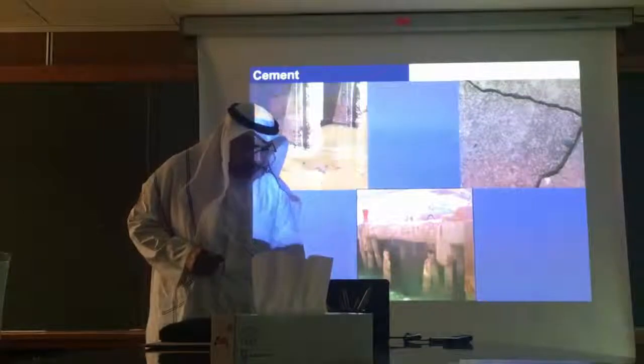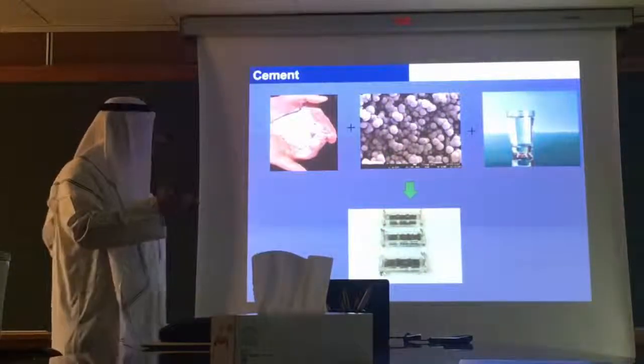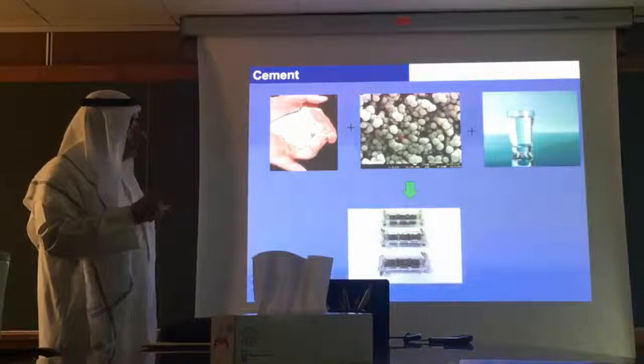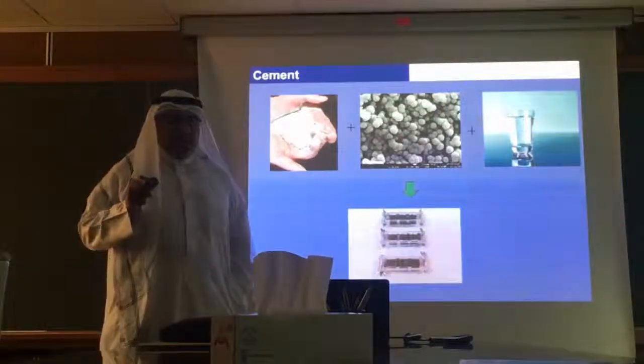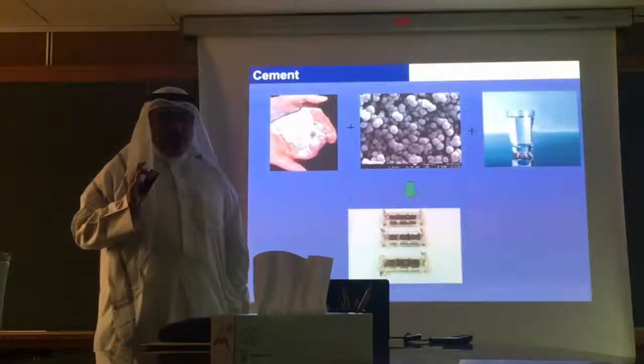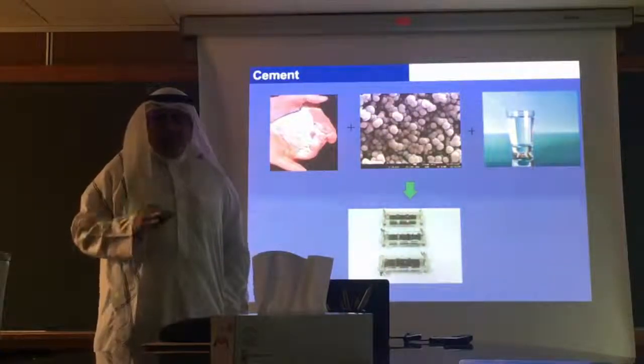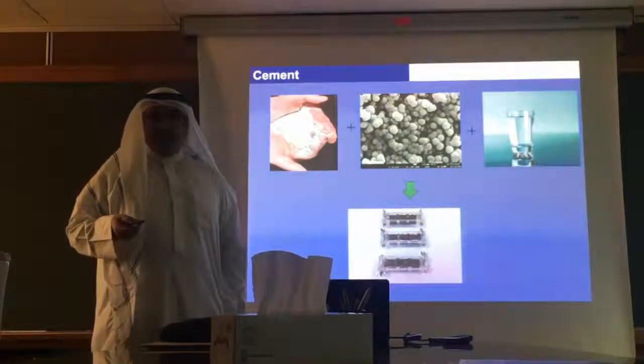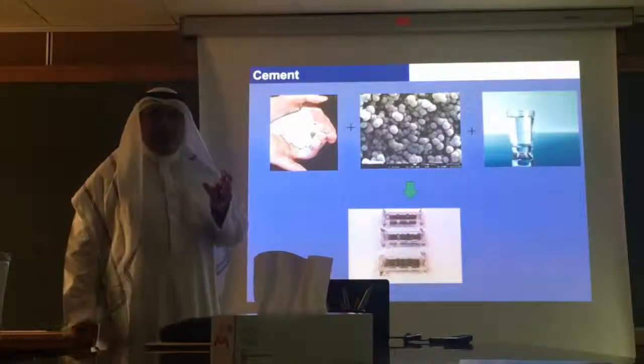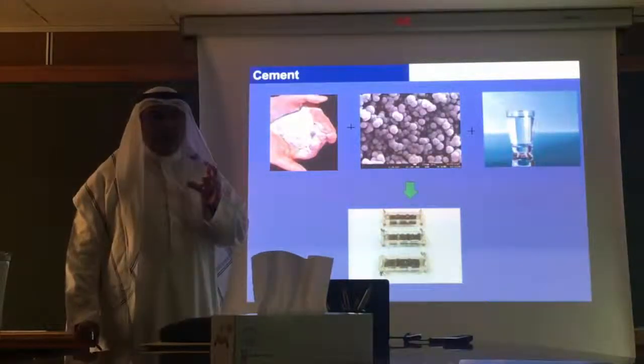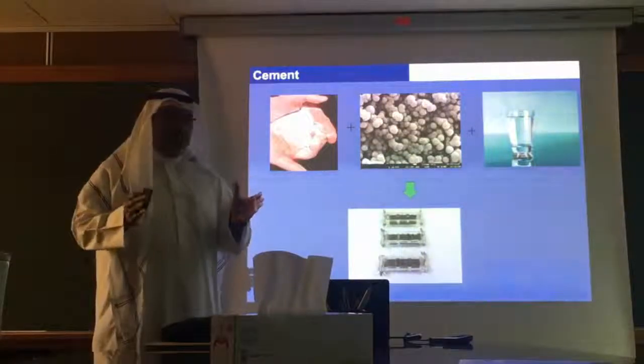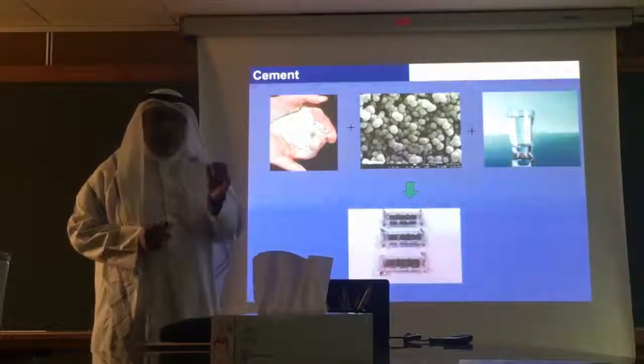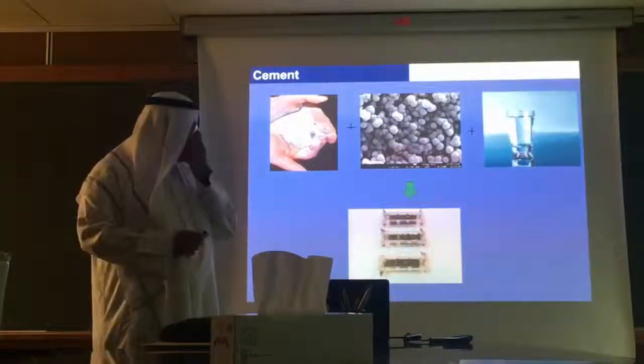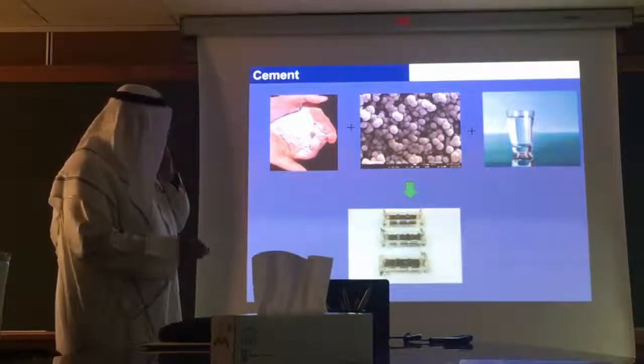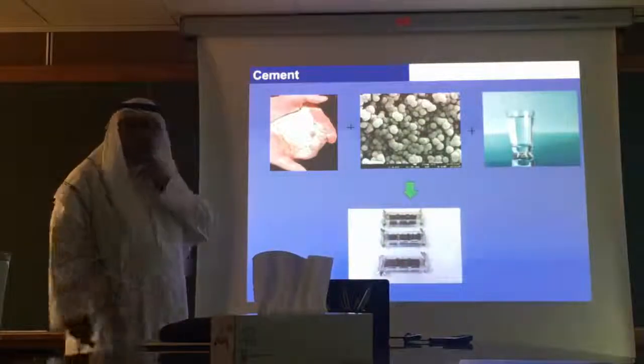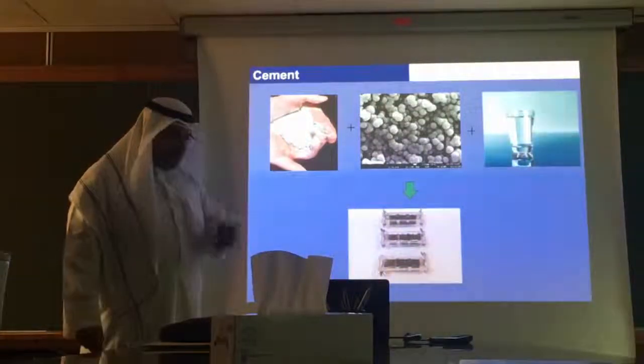So what we did, we prepared nanoparticles. One of my PhD students prepared nanosilica. Silica is one of the main compositions of the cement. But if you add nanosilica, usually most of the research uses large particles, which they call silica fume. In this work we prepared around 60 nanometer nanoparticles, and we mixed them with the cement, and we just cast it, and then we studied its mechanical property.